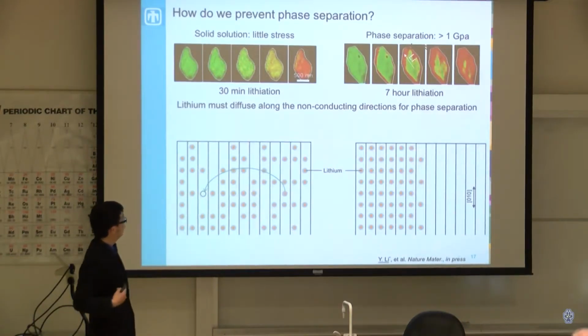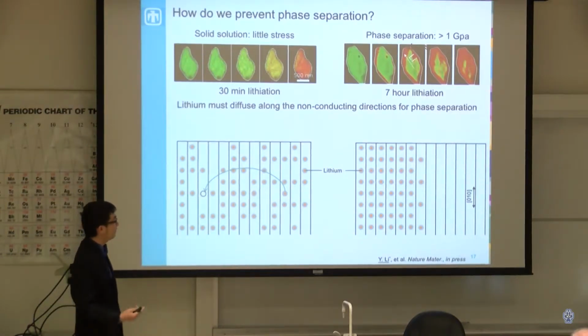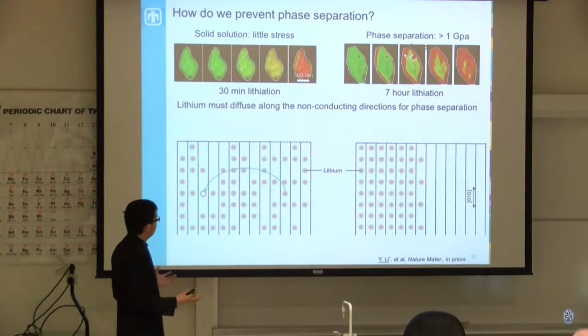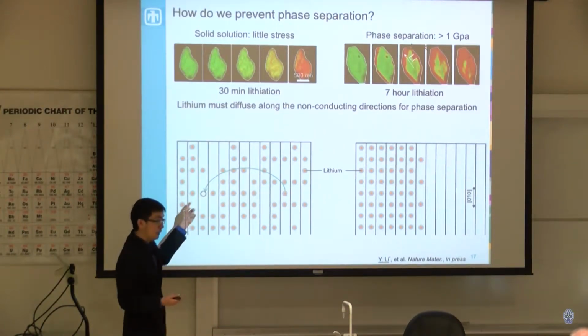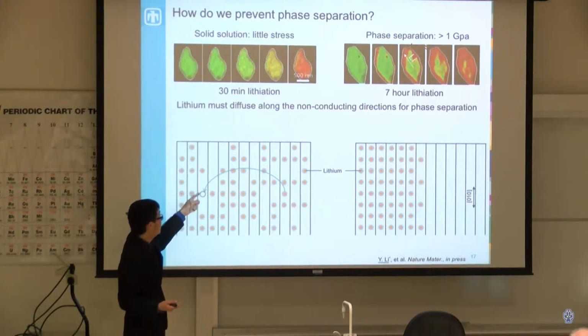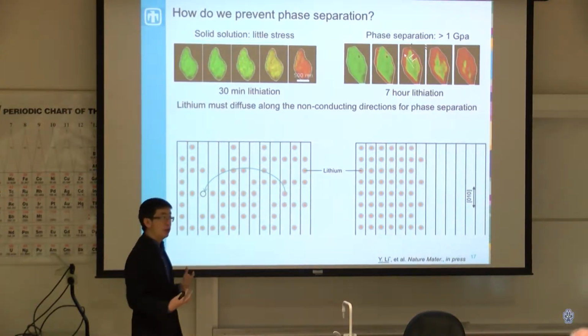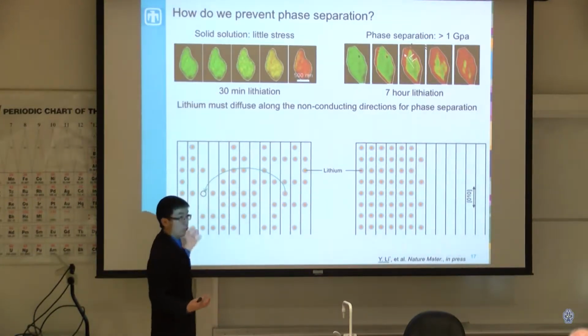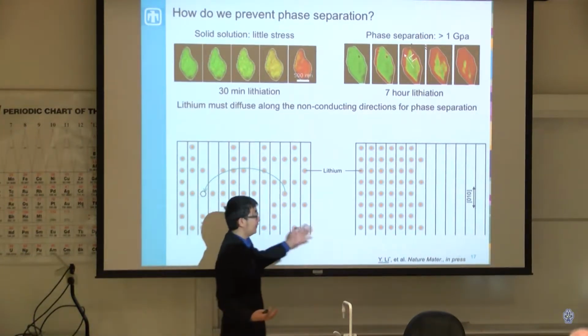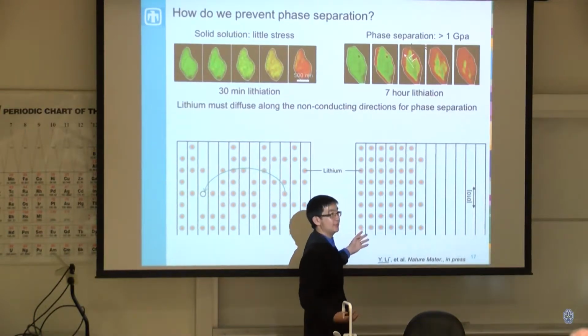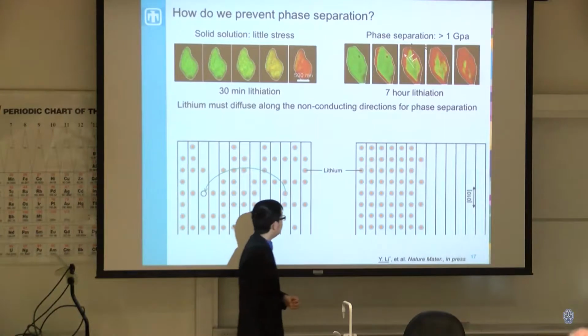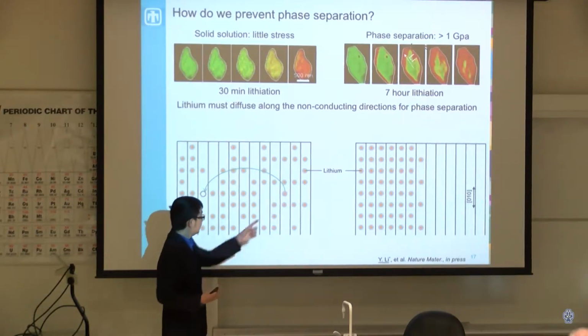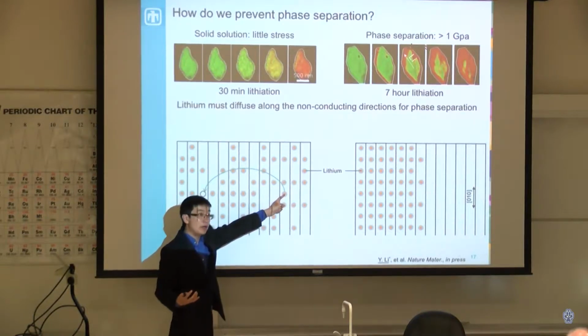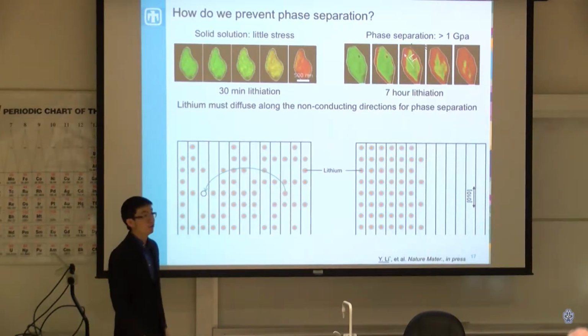To do that, we look back at the crystal structure and what it fundamentally means to phase separate. This is a crystal structure of our material, in an abstract notion. An important thing to note is that there's lithium in these particles, and there are these one-dimensional channels. When we go from solid solution, we can imagine that lithium is fairly uniformly distributed within this particle. In phase separation, you have all your lithium on this side and no lithium on the other side. So for this to happen, the lithium must be able to go from one part of the particle to a different part of the particle.